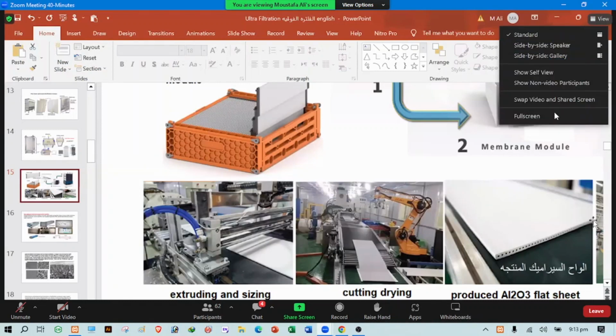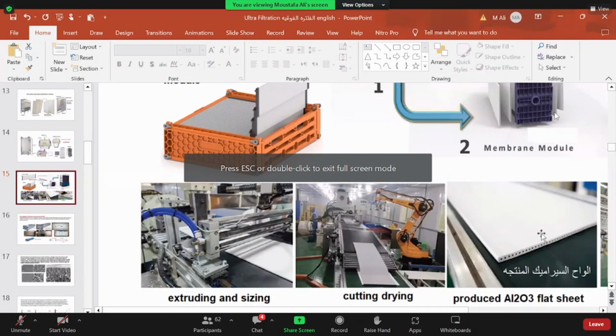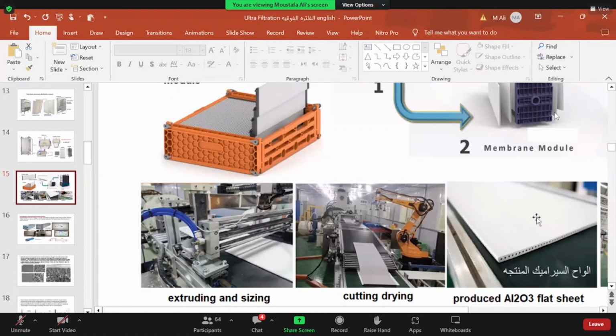It recognizes which part of the membrane is covered or not. If there is any manufacturing defect due to the absence of some spots not covered by fine layers, they can recognize it. So the robot can fix it, starting to spray it accurately. As they say, let's say with a pink color solution, with a little bit coarse 5 micron particles of alpha aluminum oxide. After that, it passes to a little bit of drying compartment, then to another compartment where another layer is sprayed with 1 micron or even finer particles, with a different color to see also that the coverage of the layer is consistent on the membrane surface as we see.